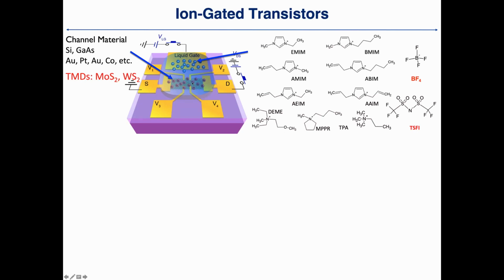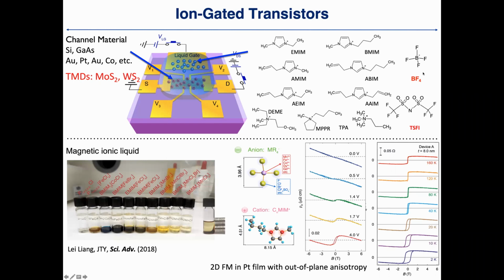Then in this particular transistor, we add one extra component called the liquid gate. Using this liquid gate, we apply a bias, then these ions start to move under the electric field, and we can accumulate carriers on the channel. So this works as a transistor. Of course, one trick you can play if you want to play with spin-related phenomena is that you replace these ions with something that contains a magnetic element. So one trick we played is that we replace this with a magnetic ion, such as manganese or cobalt.